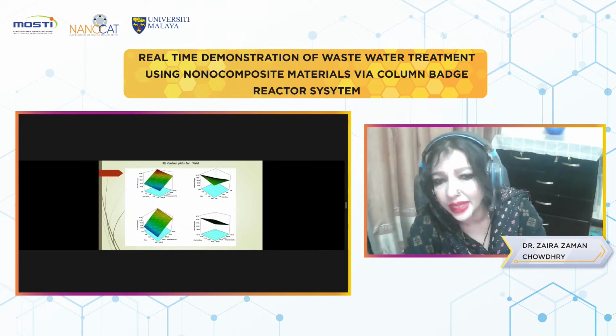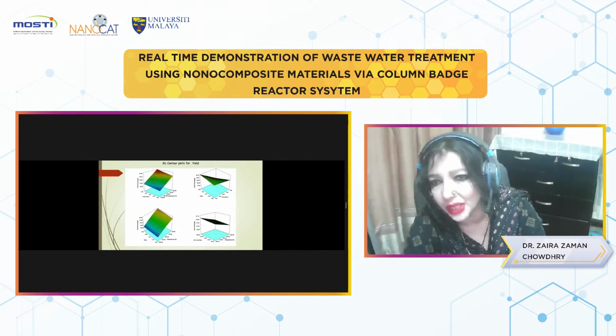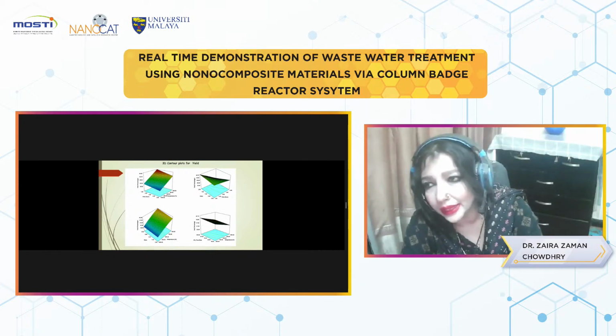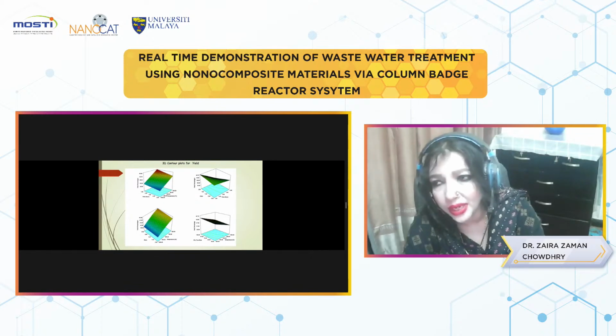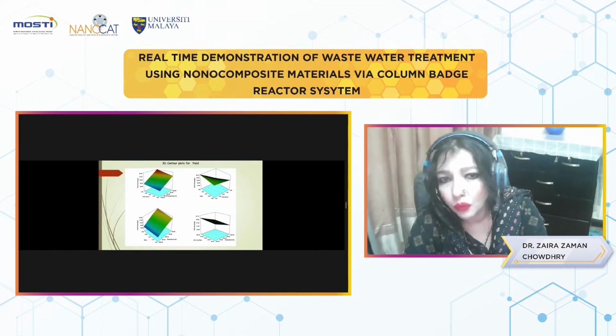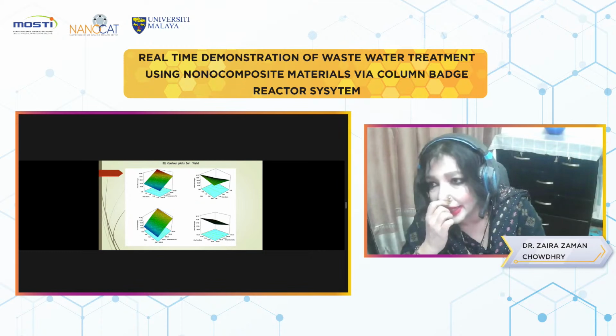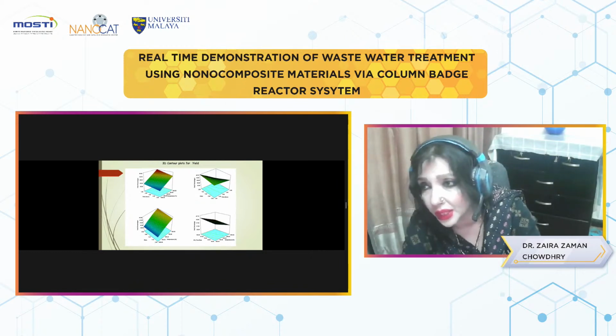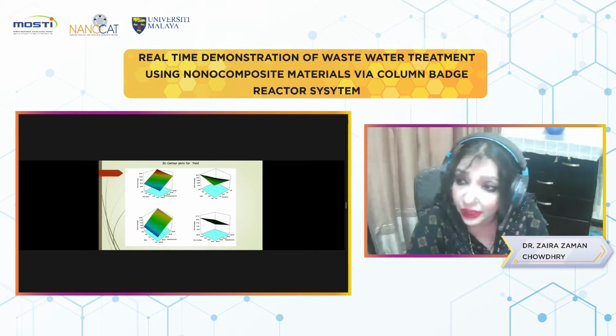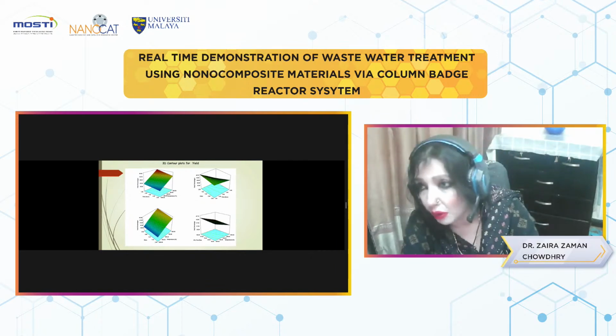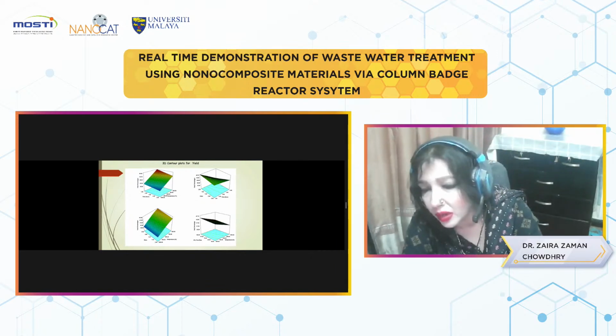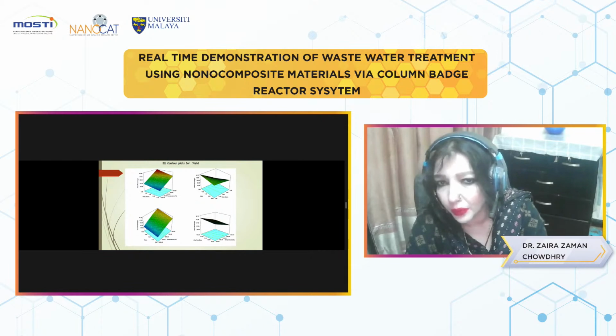Similarly, when we go for yield, we can see there is no umbrella shape. This is completely a straight-cut reaction. When the temperature is increasing, yield is decreasing. When the ratio is increasing, yield is decreasing. When the time is increasing, yield is decreasing. Obviously, there will be more reaction, more volatile material will come out, more ash will form, more sample will be burnt off, so there will be less carbon product, right?